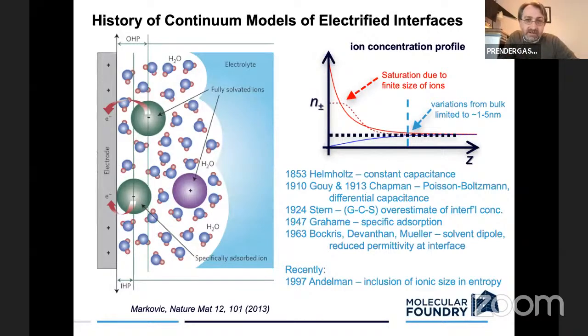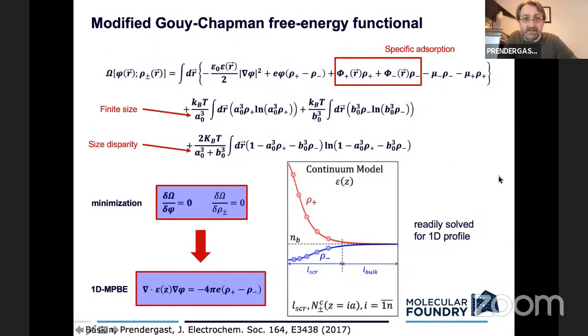What we had done recently was to try to fold all of these details together into one model. We're using basically classical density functional theory here. You can define a free energy functional, omega here, which is a function of the potential and also the density of species. So rho plus or rho minus would be the density of cations or anions. This is a simplified two-species model, cations and anions, embedded in a medium defined by the dielectric, epsilon, which is spatially dependent. And you end up solving a set of self-consistent equations based on the boundary conditions, which are the concentrations of the different species out in the bulk solution, and maybe some details you might know about the interface in terms of its ability to specifically adsorb certain species or not.